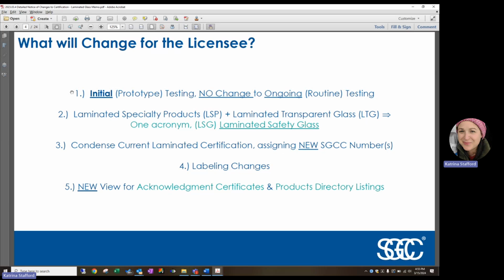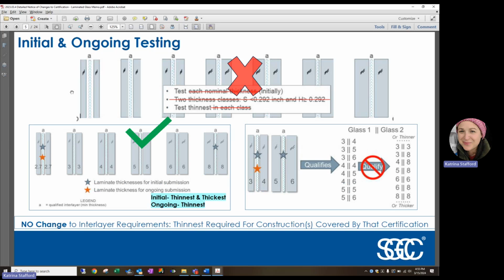It does go into, again, what changes the licensee is going to be seeing between initial testing, the removal of the two different types of acronyms to only one, LSG. This presentation also goes into explaining your initial and ongoing testing requirements. It shows you how SGCC used to certify laminated glass along with the range. If you were certified for an 8, a 10, a 12, and a 16 under one number, you had to initially submit 8, 10, 12, and 16 millimeters to get that range. Now, you will only need to send your thinnest configuration, the minimum, and your thickest configuration, the maximum, and you will be certified for everything in between.